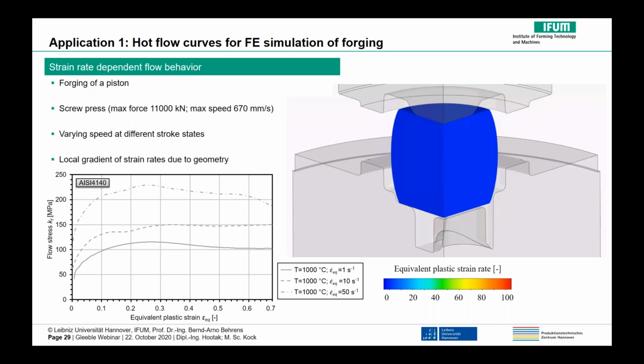Okay, because I think it looked like you were doing some testing above 1200. So did you have any challenges with those? Were they breaking? I guess they worked okay? Yeah, we saw after experiments at these high temperatures, we saw them break faster than at lower temperatures. Maybe just after 2 or 3 experiments, we had some cracking or abrasion on the surface of the tools.